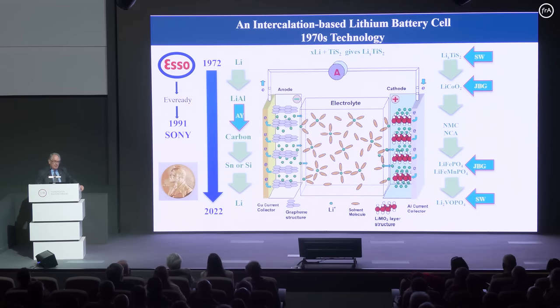Going through a little bit of the history, at Exxon, we used pure lithium metal as the anode initially. We found issues there, and I'll show you a picture shortly. You get dendrites, which can short the cells, so we switched to a lithium aluminum alloy to make it safer. But that only lasts maybe 10 or 20 recharges. So it was Akira Yoshino in Japan who really developed the carbon-based anode.